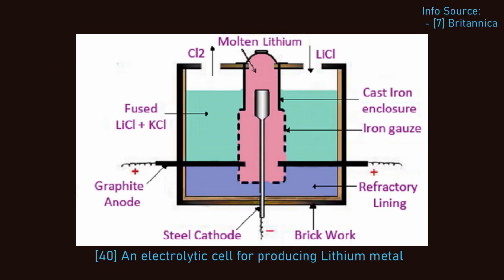The positively charged anodes of the electrolytic cell are made from graphite, while the negatively charged cathodes are made from steel, since lithium chloride has a lower decomposition voltage than potassium chloride. A voltage is used that is high enough to electrolyze the lithium chloride, but low enough that the potassium chloride is not affected. The lithium metal forms at the cathode and pulls to the surface of the cell, where it is prevented from coming into contact with the air by a thin coating of electrolyte.